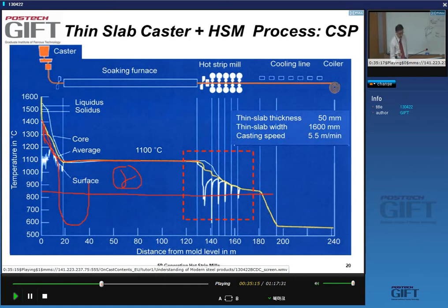And then you also have a roughing. So that's absent in this case. And a typical temperature at which you keep the bar before you roll it is 1100 degrees C, and the holding time is about 20 minutes, yes? And you can see how long these bars are approximately. They're about as long as the tunnel furnace, and the tunnel furnace is about 100 meters long. So it's a long furnace.